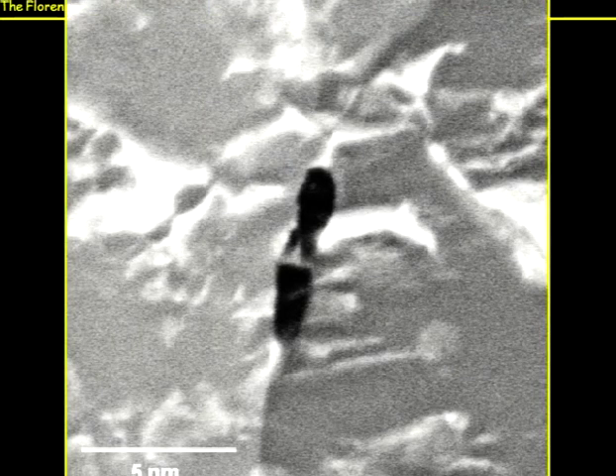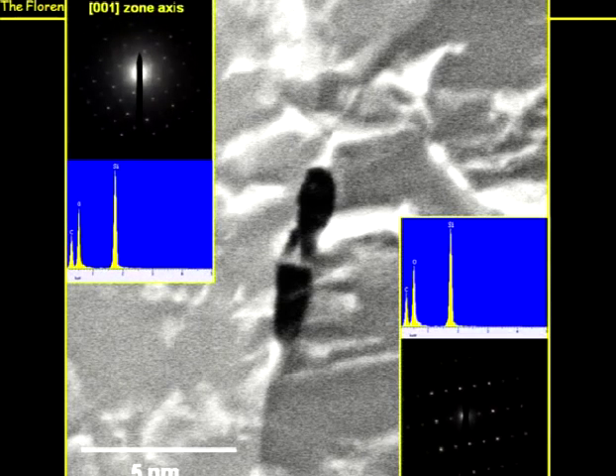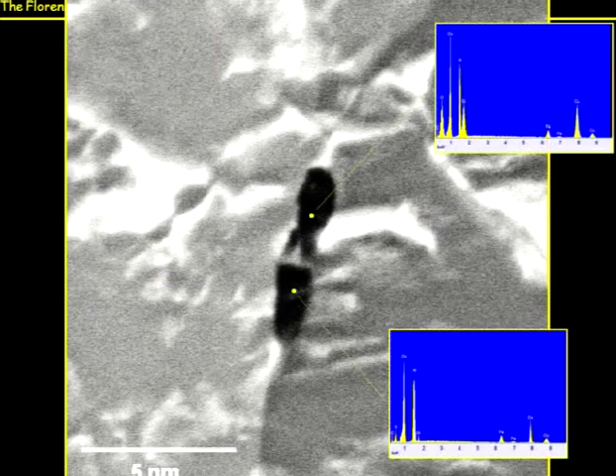What I have to show you, because it is an unpublished figure, is this stishovite grain. It is an enormous blow-up of the stishovite grain. So this is 5 nanometers, and this is a blob, a metallic blob inside the stishovite. This is silicon and oxygen only, with the electron diffraction pattern of the light gray parts. And what about the metallic blobs? Well, they contain aluminum, copper, and iron. So it is a small quasicrystal embedded in stishovite, which testifies that quasicrystals also form at high pressure.